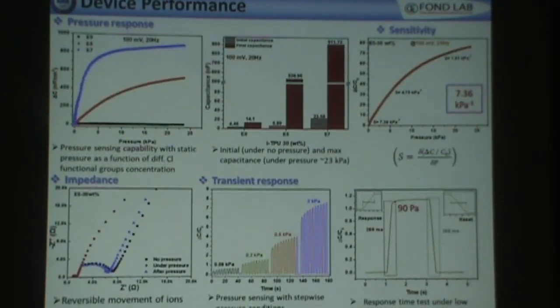So for some device performance here, we have a comparison between samples. First, we have 3 samples here: a sample without any chlorine functional group, and then samples with 58% chlorine functional group, as well as 78% chlorine functional group. As the content of chlorine functional group increases, the response to static pressure also increases, as you can see here. So this is quite effective. However, we focus on 58% chlorine functional group because higher chlorine functional group also affects the self-healing speed of our system. So we chose only 58% for any device fabrication.